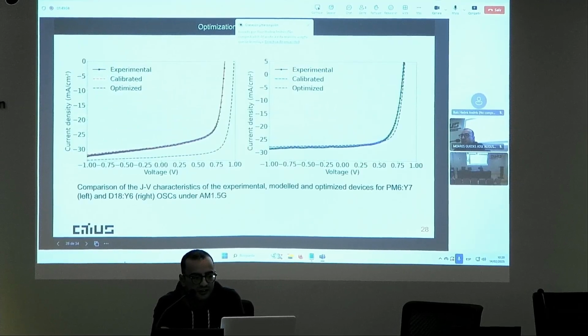Here you can see the graphical results. These figures compare the optimized, calibrated, and experimental curves under illumination. This is the figure from the PM6 organic solar cell, and this from the D18 organic solar cell. As you can see, the optimized devices show an improvement in performance compared to the experimental and the calibrated ones, especially in this case, the PM6 organic solar cell.